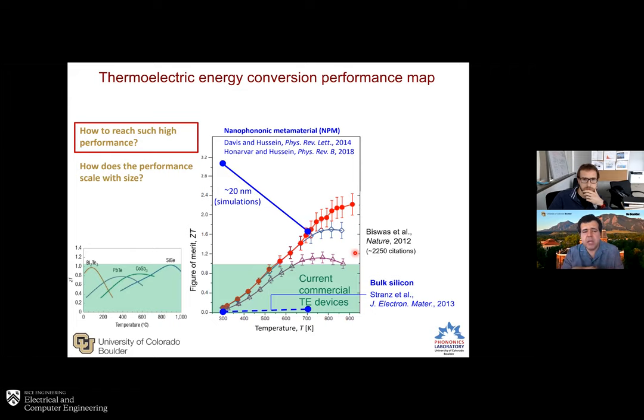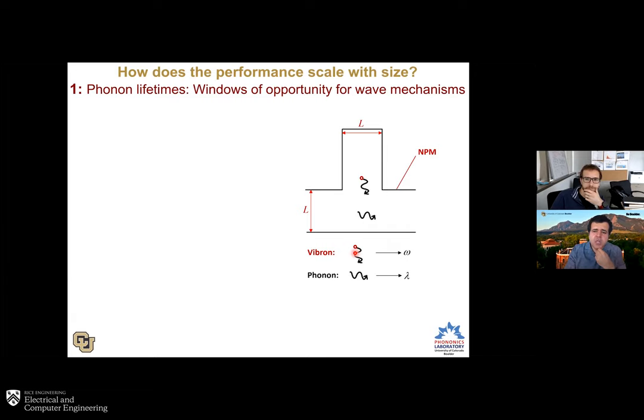Okay, so that takes care of the first part, which is essentially how we reach this performance. We reach this performance by introducing these nano resonators that couple with the phonons and reduce their speeds, localize, and so on, reduce the thermal conductivity. And hopefully, and that's what I'll address in a bit, this may all happen without affecting the electrical properties. So this takes me now to the second part, which is what happens with scale. And in fact, that's also key to the other properties for the ZT figure of merit. So there, we need to look at this scale issue from two perspectives. There's two aspects to it. One of them I've touched on earlier, which is to do with the phonon mean free path. So I want to dwell on that a little more.